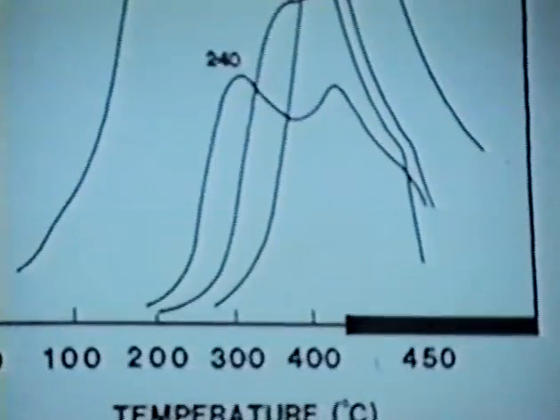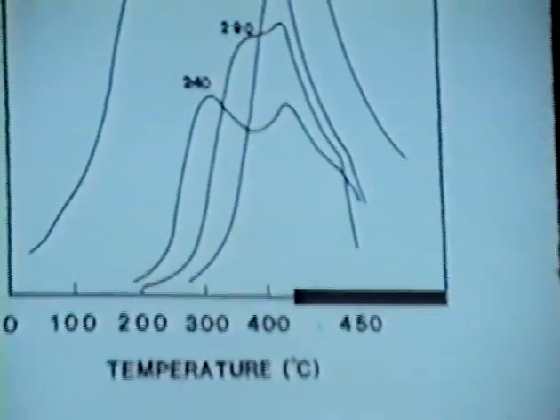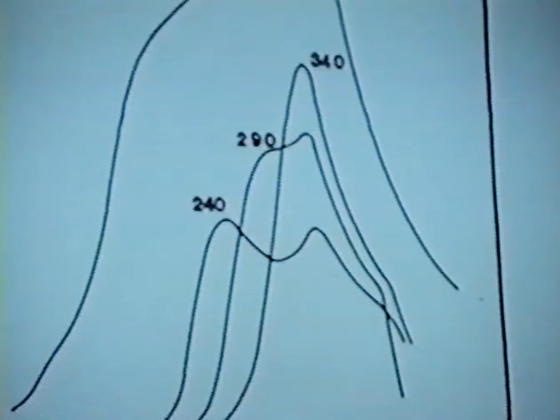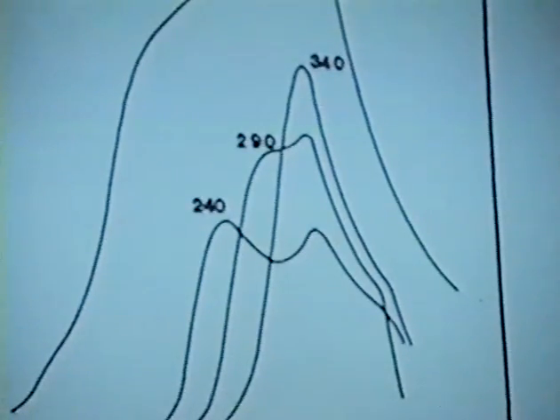In the case of 15% iron on silica promoted with 3% potassium, we observe an even greater effect — no adsorption at all below 240 degrees centigrade, and an increase in amount adsorbed up to 340 degrees centigrade. There is a new peak at about 400 degrees centigrade, indicating a very strongly bound hydrogen adsorption species. When cooling in hydrogen from 450 to 25 degrees centigrade, we see many more times the amount of hydrogen adsorbed. We think it is probably the influence of potassium species on the surface that perturbs the electronic states of the metal surface and results in this highly activated adsorption.